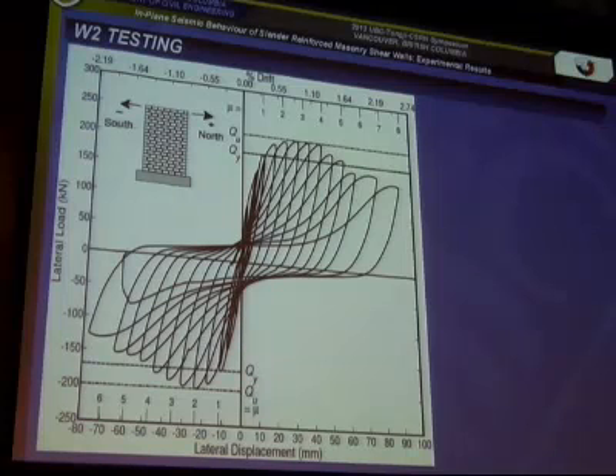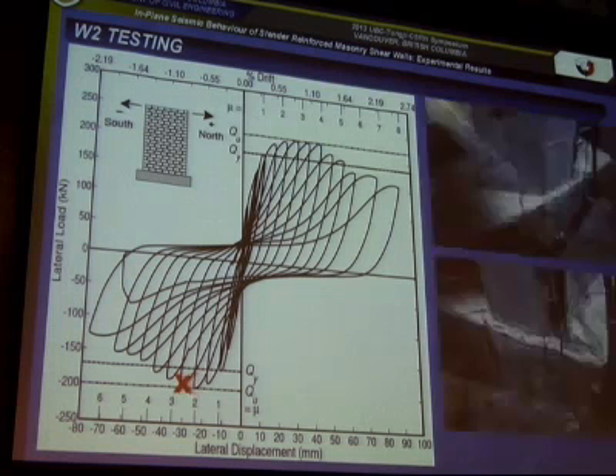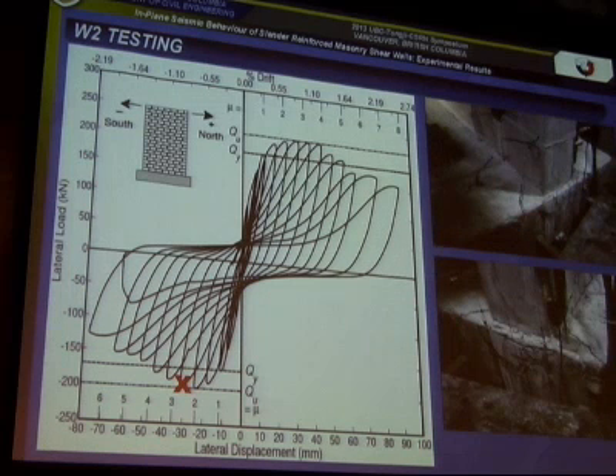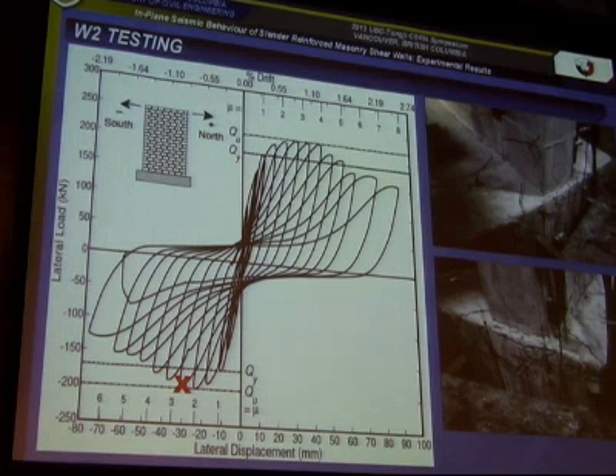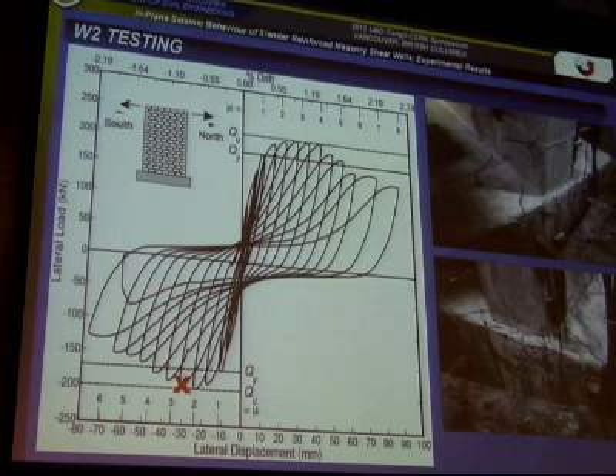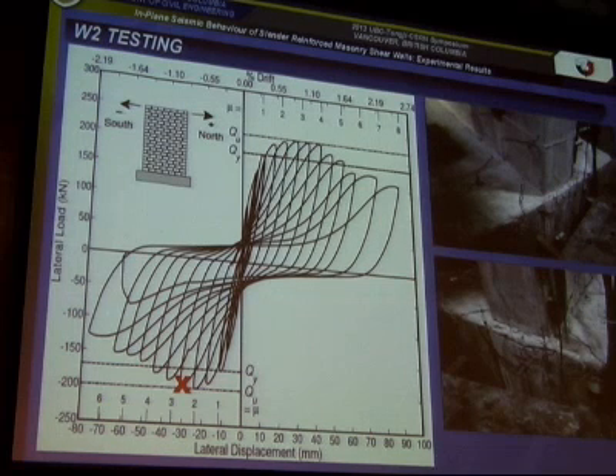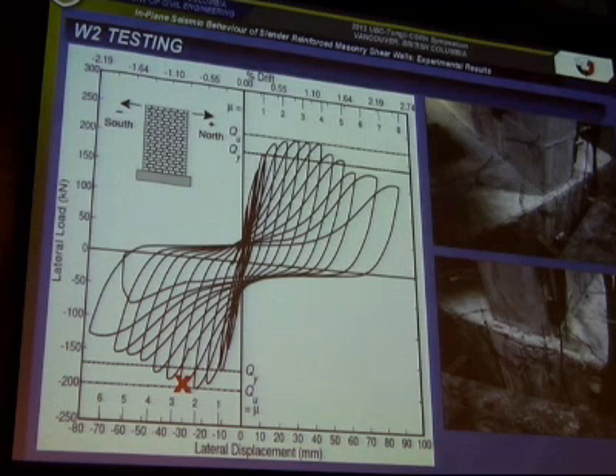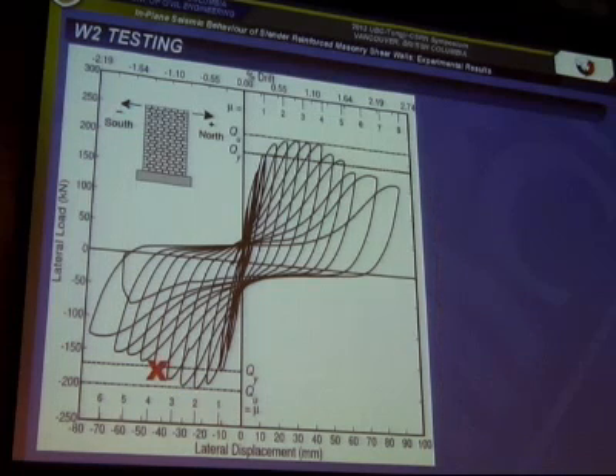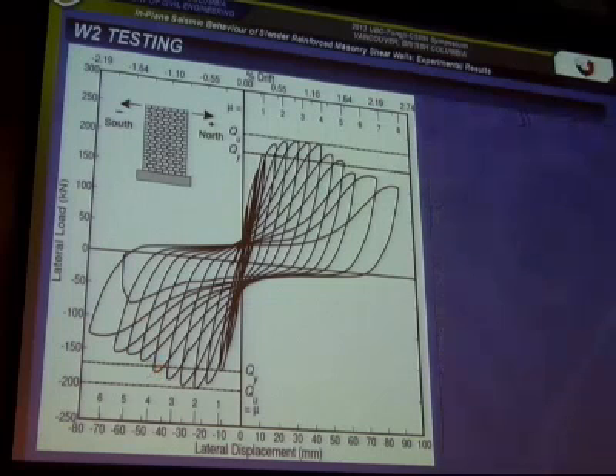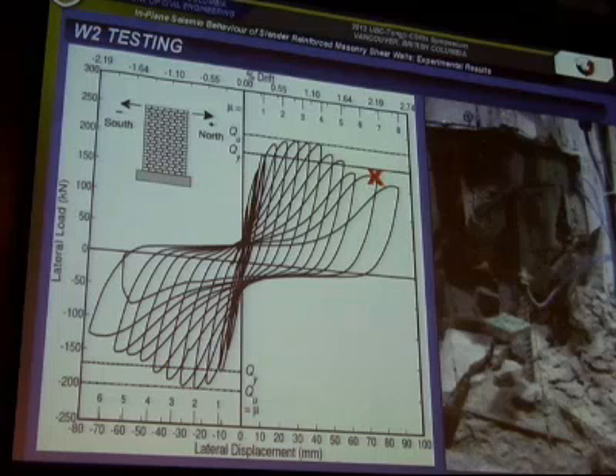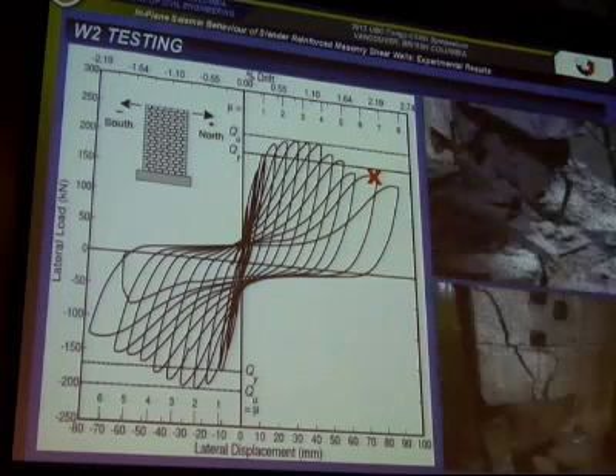So looking at the response, it was much better. There wasn't much damage until the base sliding at the toe caused the toe to extend past the footing, which is my design error, the footing reinforcement, and caused cover spalling of the footing. And this caused some asymmetry in the response, but toe crushing continued on both sides afterward. And the face spalling actually allowed us to see the straightening of the reinforcing bars when in tension, and then the buckling of these bars when in compression.